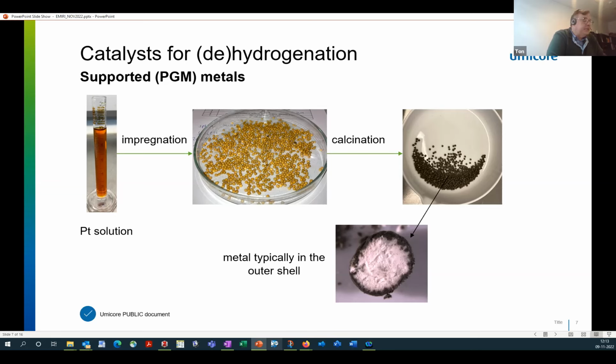And I think the spheres here are actually a high surface area alumina. You dry them, heat them, calcine them at about 400 to 500 degrees. Then they turn black. And the black is because of the metal particles. So in case of platinum, the heating will lead to formation of some metal oxide, and with the metal outside on it. And you can see in the sphere, the platinum will typically be located at the outside of the spheres, which is good because that ensures good contact to the oil.